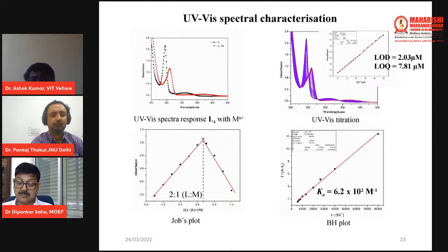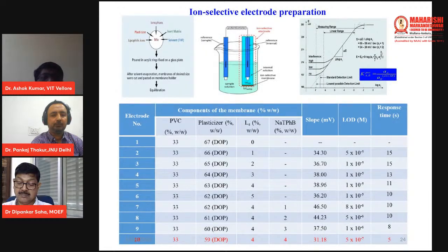With that idea, we started to prepare a liquid membrane electrode. We prepared the liquid membrane electrode with a well-established procedure, and we set up this electrochemical setup. From this setup, we analyzed the thorium concentration, and it fantastically behaved in a Nernstian manner. This entire composition study is to establish the Nernstian response. One composition, where the ligand is around 4%, worked out for the exact quantification purpose.